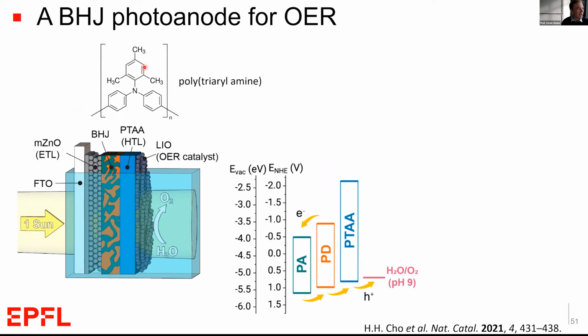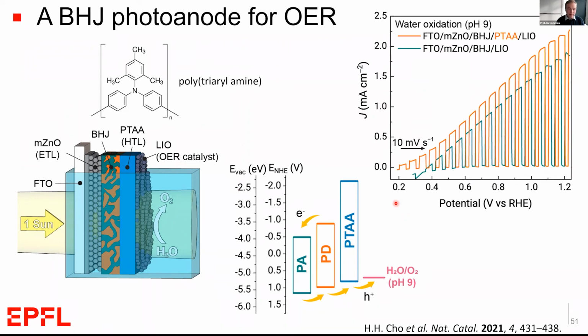And by putting an overlayer here of this other PTAA organic material to help extract the charge carriers and reduce the accumulation of charges in the bulk heterojunction, along with a catalyst, a lithium-based iridium oxide catalyst for the oxygen evolution reaction, to achieve an impressive first demonstration of a photoanode using this bulk heterojunction concept with a photocurrent already of about 2 milliamps per centimeter squared. So not far off of even the hematite-based electrodes.